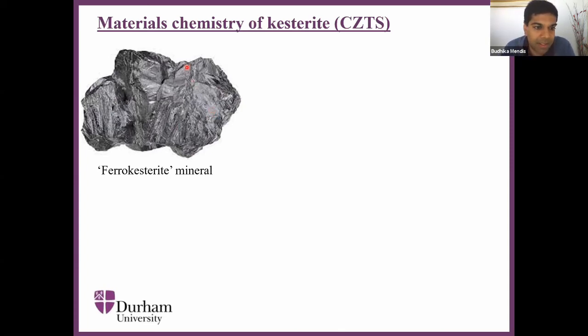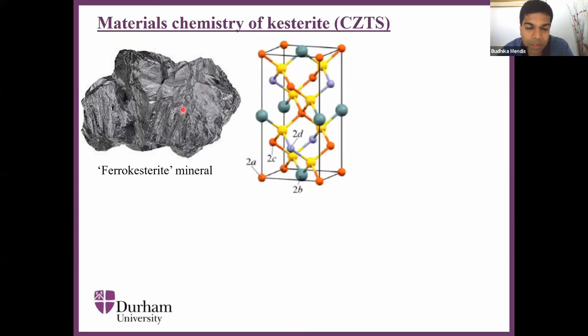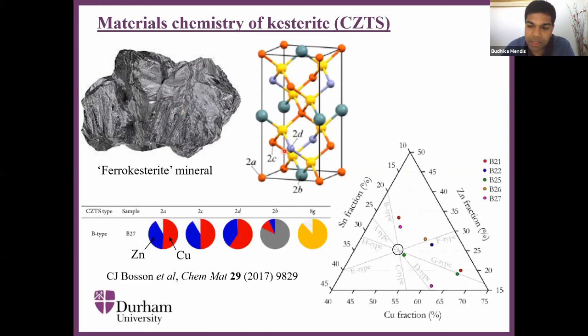You can see that it is black in color, which is good because it indicates that it's absorbing the light very strongly. So we can make thin film materials out of this. Unfortunately, although it looks promising on the macro scale, when you look at the individual atomic scale, then you run into difficulties. So this is work that was done by my colleague, Dr. Douglas Halliday, looking at atomic scale defects in this material.